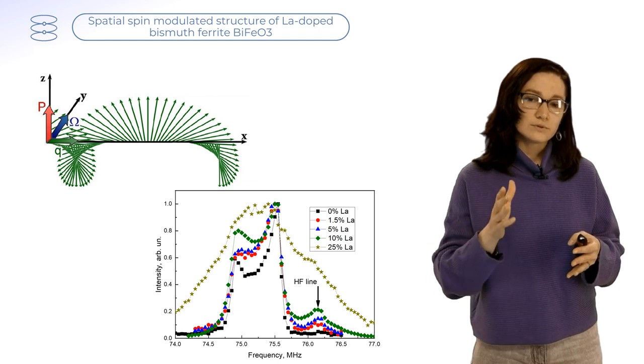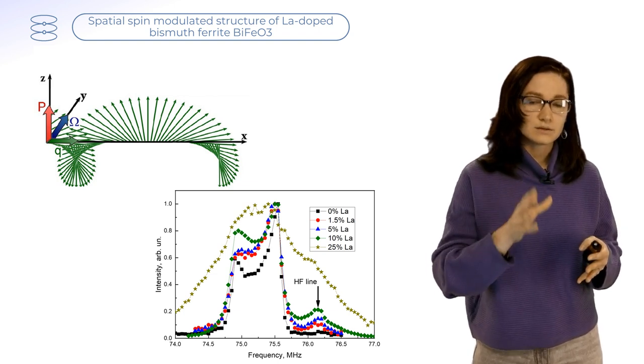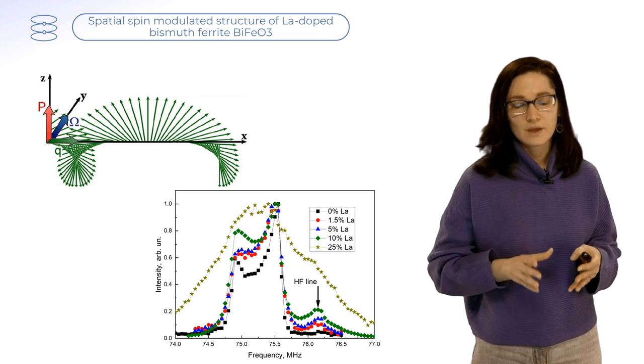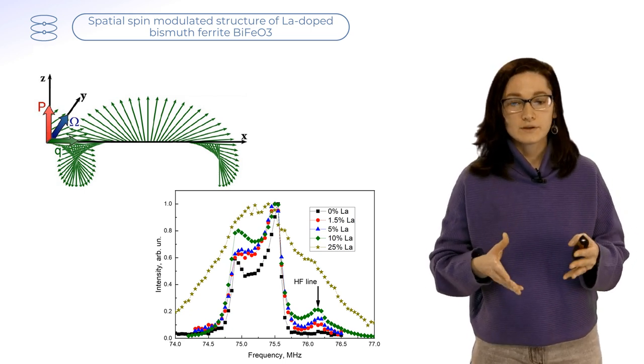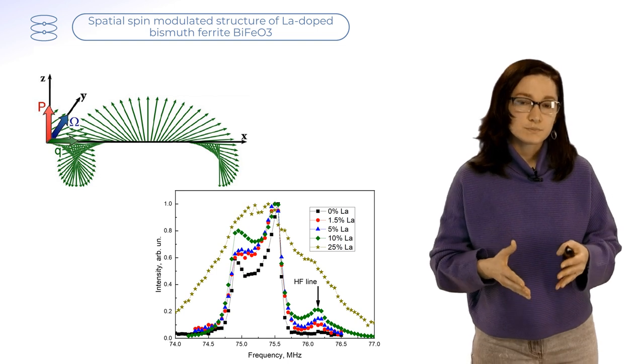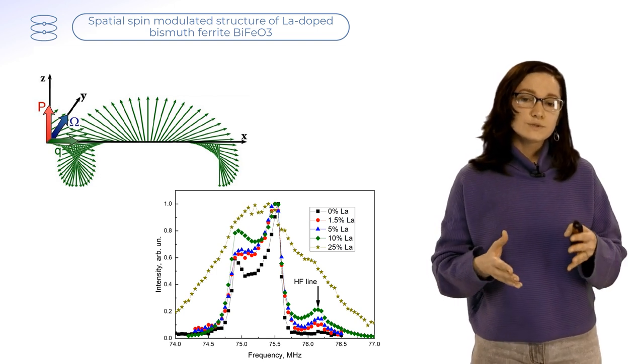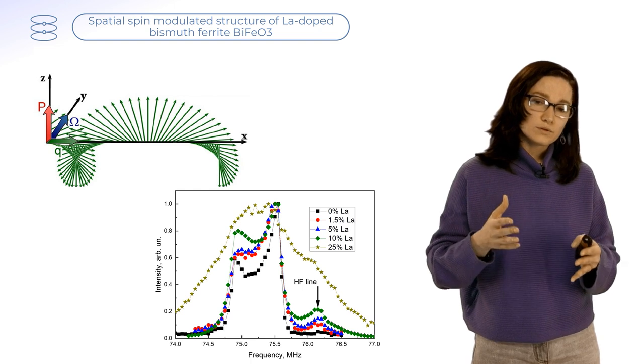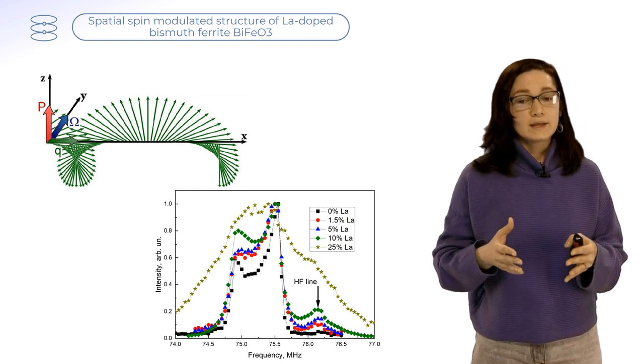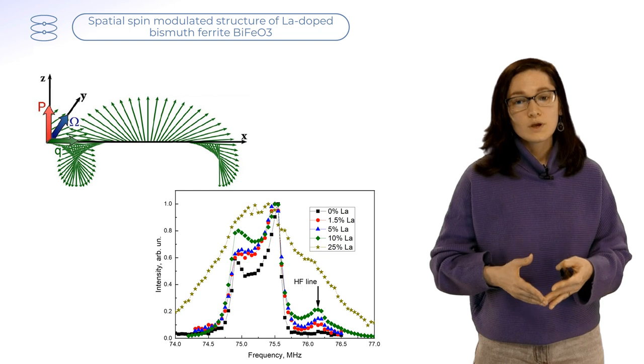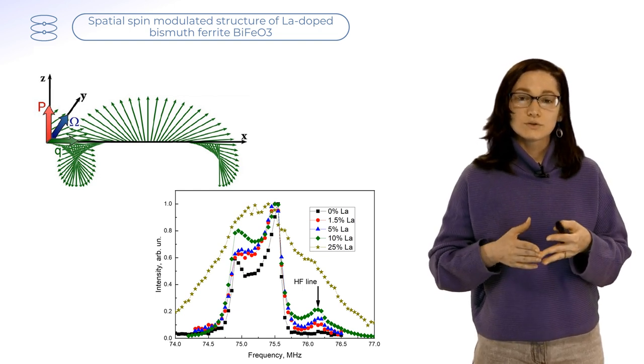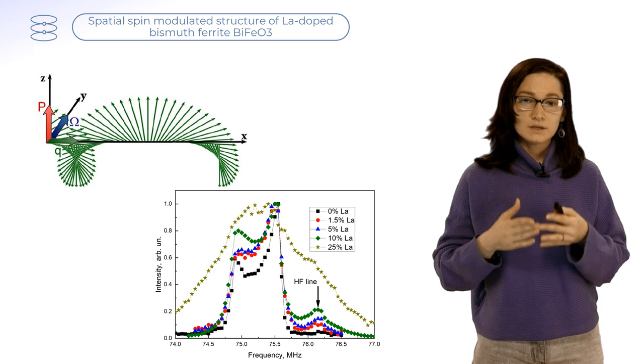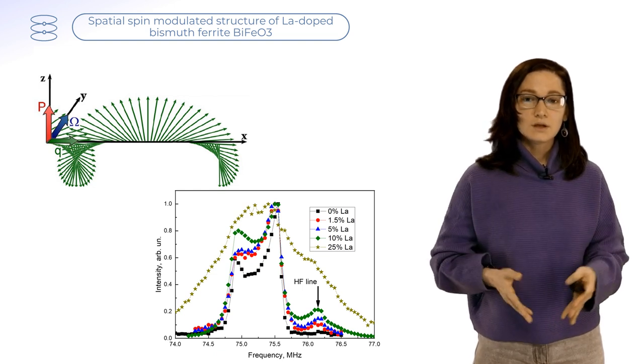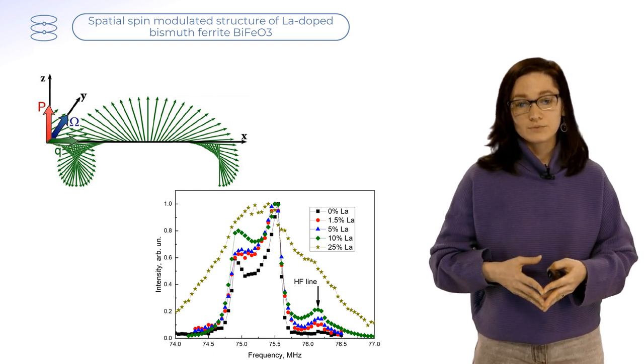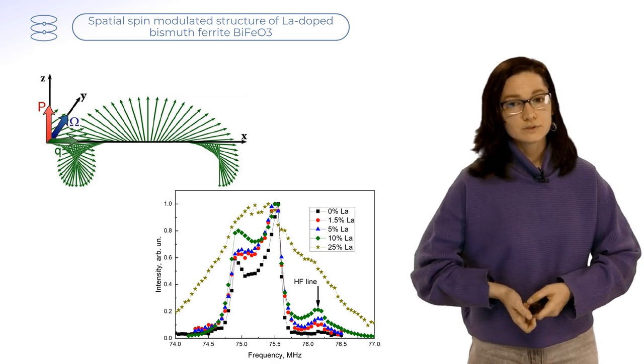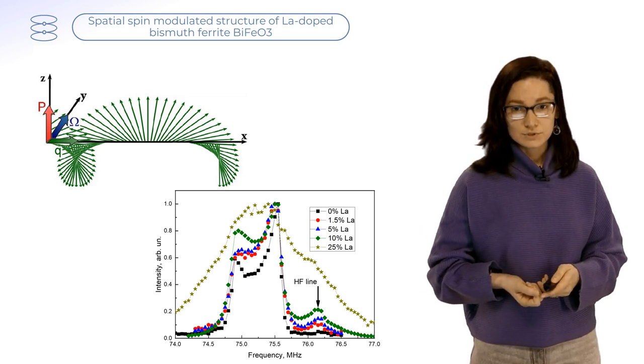You see it best on the black squared spectrum. But upon doping by lanthanum, the structure of this spectrum modifies, and we see that the peaks become more equivalent. And at 25% doping, we see that this structure no longer exists. It has gone. It was suppressed by lanthanum doping. These measurements were supported by magnetization measurements later.